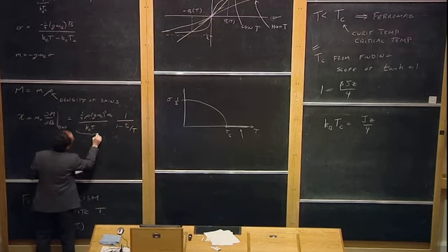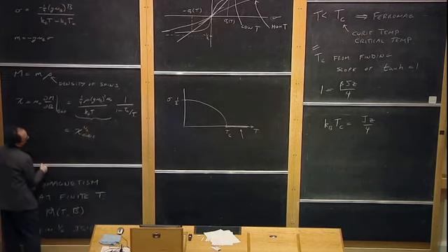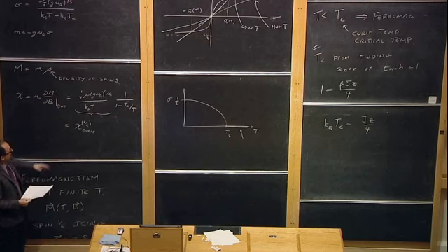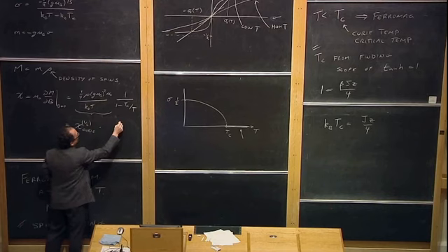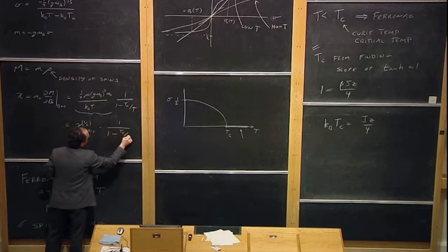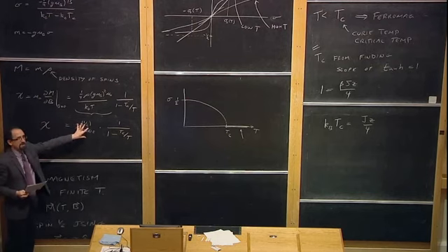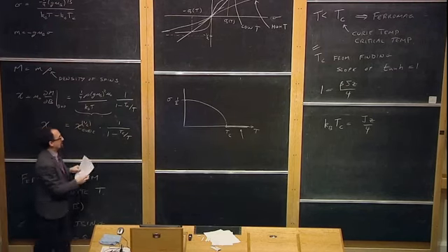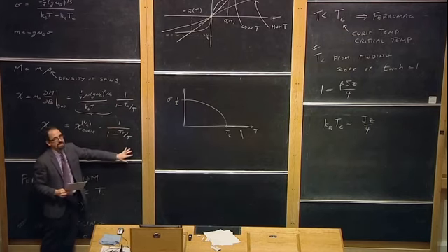And this whole quantity here is actually the Curie susceptibility for a spin 1/2. In other words, it's the susceptibility we would have calculated with just a free spin 1/2. In fact, it is exactly what we calculated when we calculated the magnetic susceptibility of a spin 1/2 in the last lecture. But then this whole thing gets multiplied by 1 over 1 minus T_c over T. So the susceptibility of our paramagnet above T_c is the susceptibility of just a system of free spin 1/2s, which aren't coupled to each other. And the effect of the coupling in the Ising model, at least within mean field theory, is to multiply it by this factor of 1 over 1 minus T_c over T.